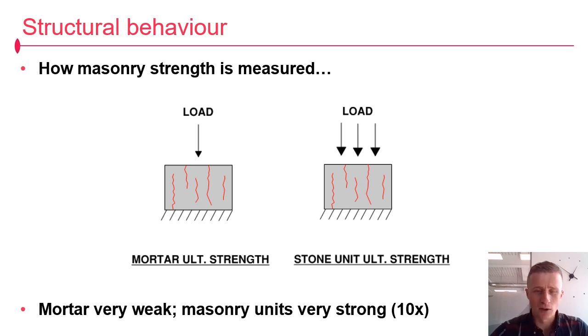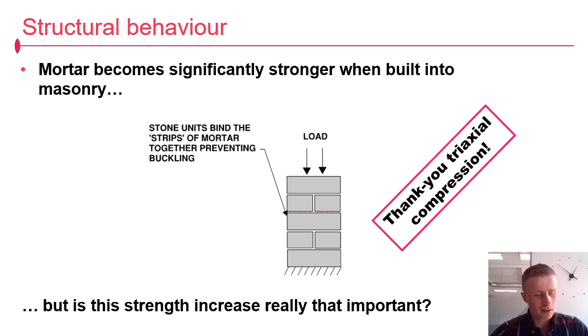Stone masonry units, similar process, but it's significantly higher strength. You're talking a clear order of magnitude between mortar and masonry unit. But it's a bit more complex than just the dilution of a weak material with a strong material. Like I said, the stress transmission through the joints, you're thinking, where does this go? Well, when you actually build mortar into masonry, the actual mortar strength in practice significantly increases, because each masonry unit laterally binds or clamps together the head of those wee columns that are trying to form, so they can't buckle. So the mortar is actually in a state of triaxial compression and can support significantly higher strength. So you can get very high strength masonry out of very low strength mortar.